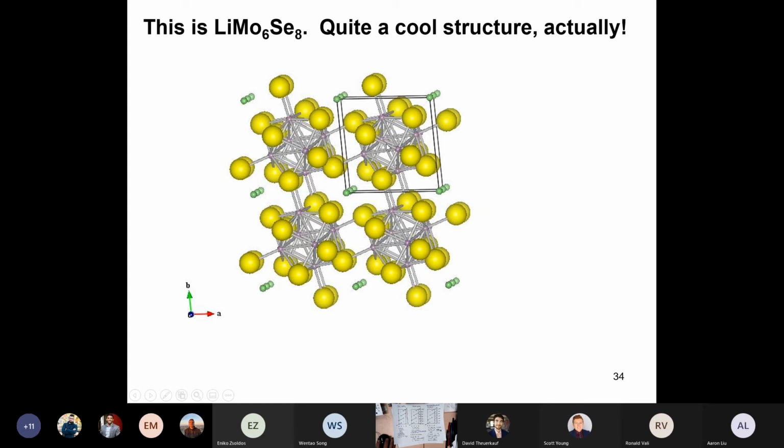And what's interesting about this structure is the lattice constant is big. It's about 8.5 angstroms. So the lithium-lithium near neighbor distance of this thing is about 8 angstroms. It's huge. With lithium cobalt oxide, the near neighbor lithium-lithium distance is 2.8 angstroms, so it's very close. Similar in spinel.